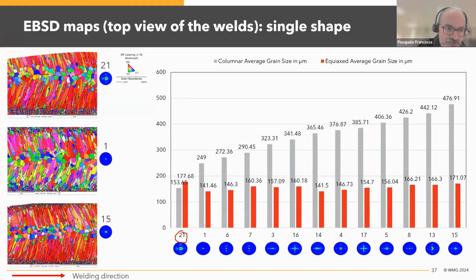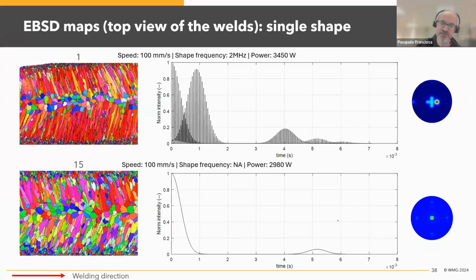But comparing 1 and 15, the columnar grains are quite high in aspect ratio. In 15, the aspect ratio is quite reduced. They are pretty much distributed along the y-axis. So the reason why there is a change in the aspect ratio of those columnar grains is probably imputed to this effect. So the effect of modulating, pulsing, if pulsing is the right term to use in this case, but the possibility of modulating the heat intensity, the intensity distribution as you are passing through with the laser beam. And this is exactly what is happening.